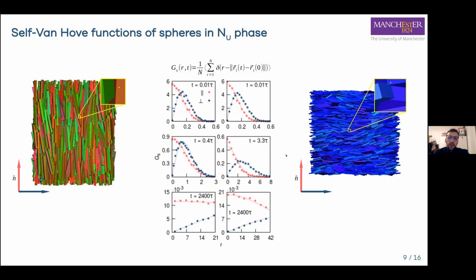To have an idea of how strong these deviations from the Gaussian distribution are, we computed the self-part of the van Hove function of the hard spherical tracers in these uniaxial nematic phases. And as I said before, we observed higher deviation from Gaussianity at intermediate times, and specifically for the diffusion of hard spheres in the direction parallel to the nematic director in oblate nematic phases. As you can see here from the dots reported in red in this case, which are the data of the van Hove function directly computed from the simulation, that deviates from the line which represents the expected Gaussian distribution in this case.